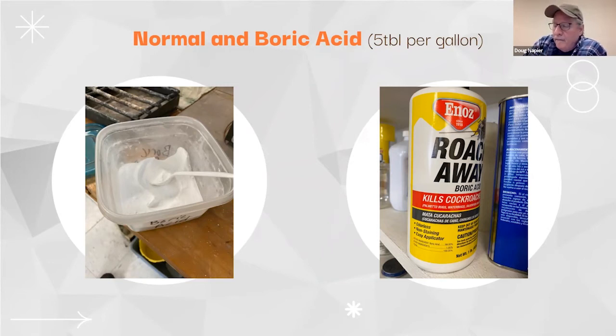So now in investment, there's a couple of types of investment that I use. I'll use just regular straight Satin Cast 20 or the R&R Ultravest. And I've never really used the platinum based ones because I can get the same effect if I add powdered boric acid to my investment. And instead of adding it to the investment, what I actually do is I add it to my water. So I've got a jug of boric acid water that I use for casting the resins. And I usually only do it on the pieces that have detail and stuff like that.